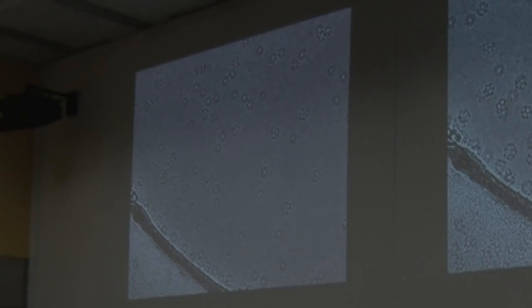It's 1.5 megadaltons, and it's icosahedral, and you can see the twofold views, the fivefold views, threefold views, and then this is the hole in the carbon film, blotted by the Dubochet plunge freeze method. And you can see the orientations easily. And then as you come down in size, the amount of information in each image of each particle gets less. So it's harder to find the orientation.